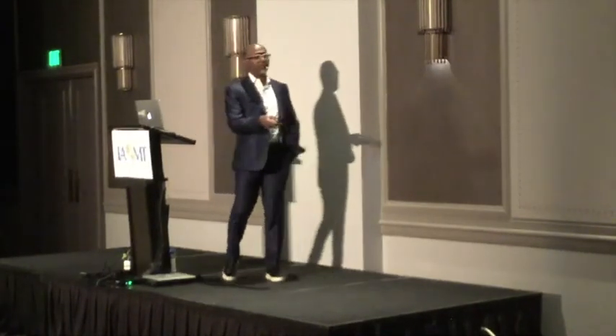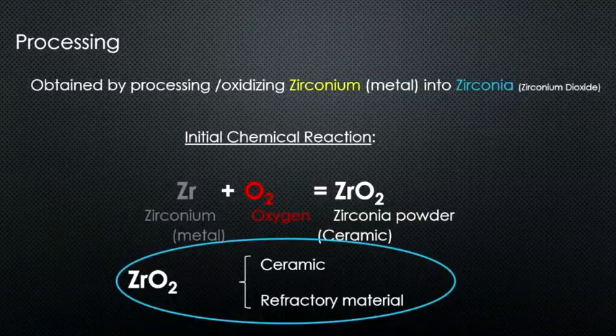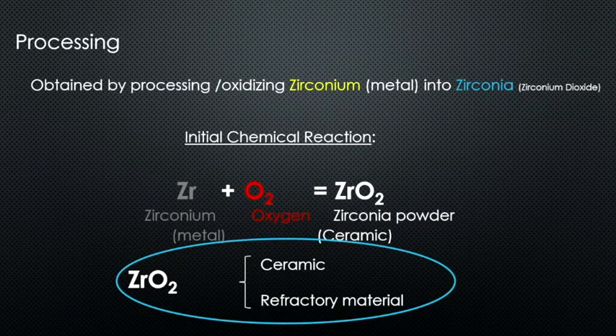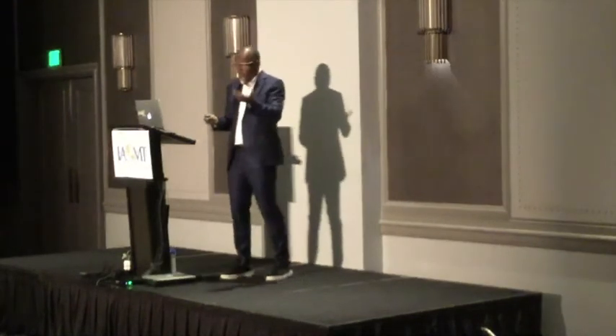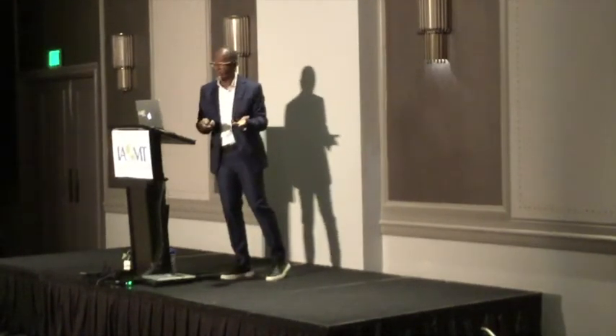So again, the basic chemical reaction that happens is that the zirconium is exposed to oxygen, and then you get the zirconia. Like when they tell you, you open the titanium implant, you expose it to the air before you put it in the bone, and there's an oxide layer that forms. Well, that oxide layer is called titania, because this oxygen exposed to the titanium gives that layer a very thin angstrom, the oxide layer, which is a ceramic layer, titanium dioxide. Okay?